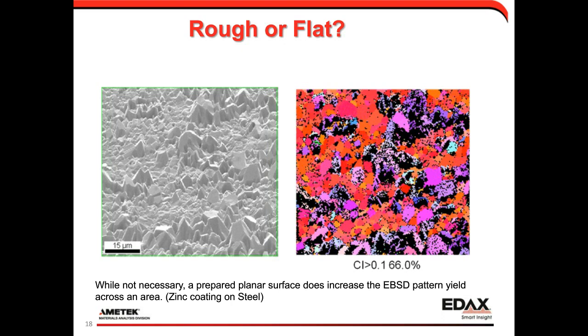The points where we don't get patterns are basically points where the beam hits the surface, but there's not line of sight from that point to the EBSD detector. It's just blocked by the topography of the sample. So while we can analyze rough surfaces, and in some cases it's required, we can improve the yield of samples by flattening them out to reduce these topography effects, while at the same time removing deformation.